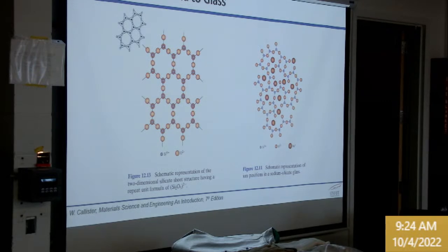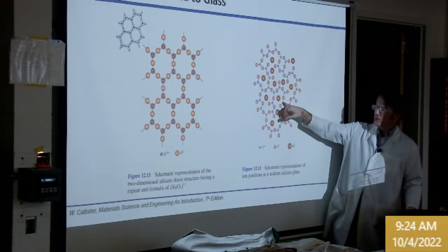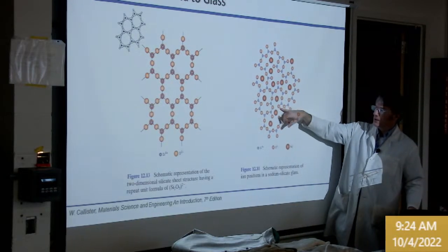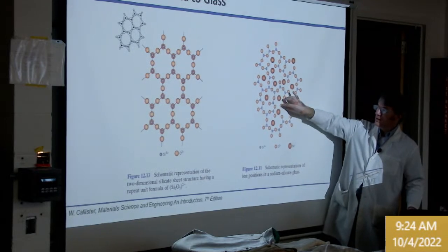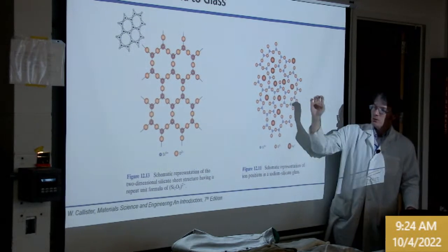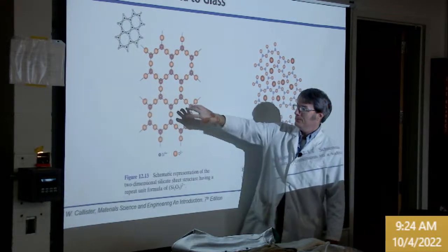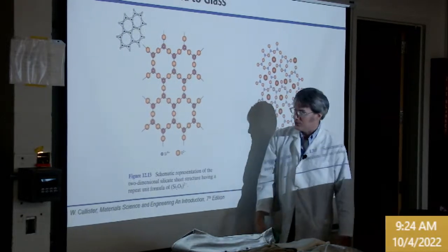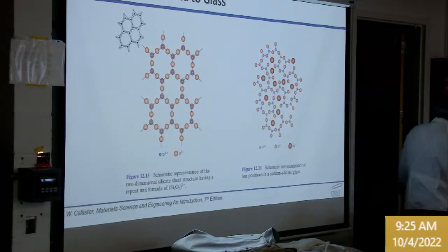So these cartoons here from the Callister text show kind of what that would look like, not quite drawn to scale, but the high regularity of the parent silicate is interrupted with our ionic centers there, the sodium ions. They're still tetrahedra. This would be a little tetrahedron of silicon and oxygen. So locally they still look kind of similar, but the long range order is no longer translatable. You know, that this is a translatable crystal structure. That breaks down, no longer the case.